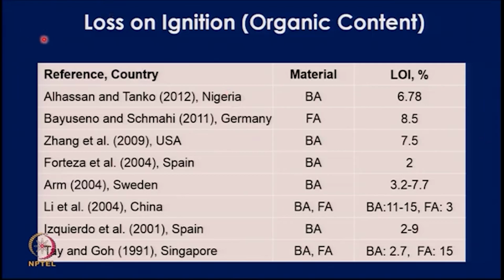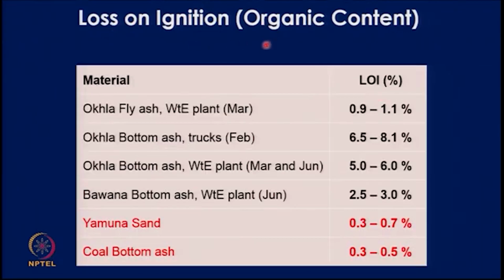If you look at the data reported in literature on loss on ignition in the muffle furnace, then in the incinerated ash, the LOI can be as low as 2%, but it can be as high as 15%. That means all the organics are not completely burnt in the incineration process. Some values are now coming in from the 2 waste to energy plants in Delhi, and what we observe is that the LOI can be as low as 0.9%, but can be as high as 8.1%. This also seems to be dependent on the weather conditions during the cold months, the winter months like in February. Burning of the organics may not be as efficient, whereas in the summer months, let's say June, the burning of the organics may be more efficient.